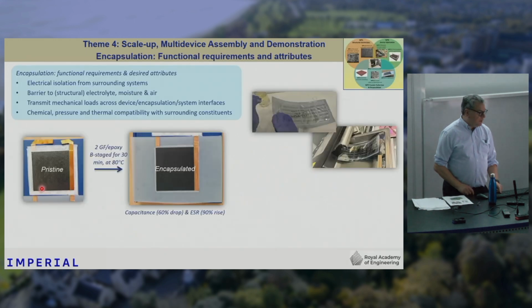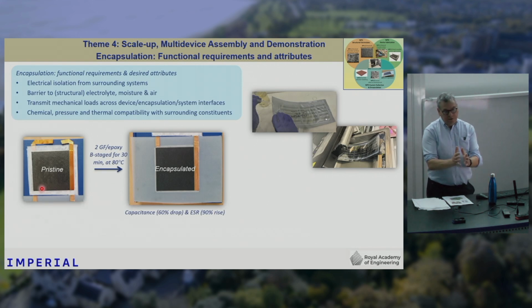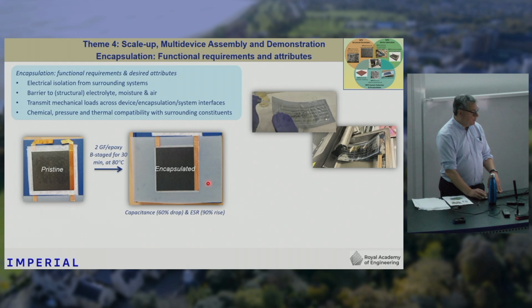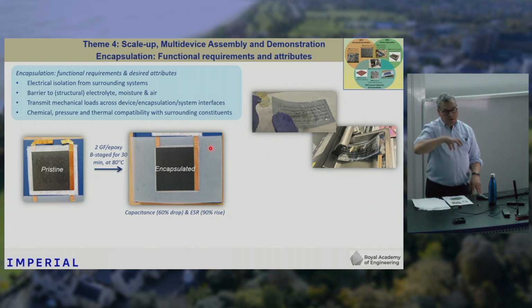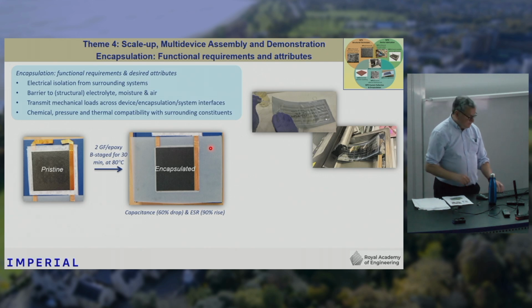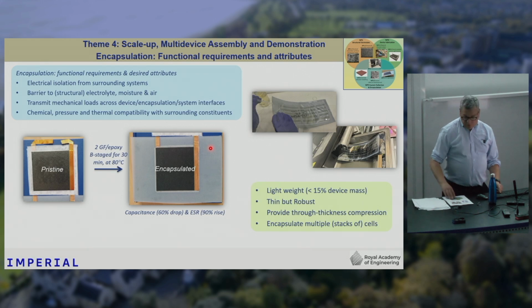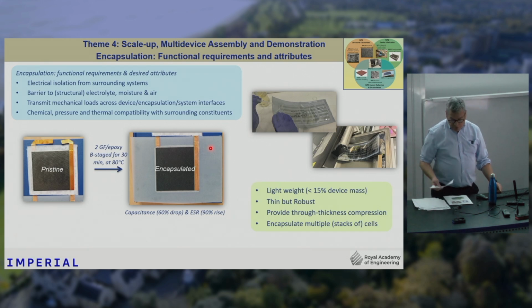And then the final challenge is to do with encapsulation. So we've made the device, but it's electrically active, and the electrodes and the electrolyte are exposed to the atmosphere, and they shouldn't be. So we need to encapsulate it in something. The first thing we thought we'd do is sandwich it between 2 layers of glass fiber prepreg. But what we found is that the glass fiber prepreg sucked out all the ionic liquid and killed the device. So we're now working on strategies to identify encapsulation solutions which will resolve this particular issue.